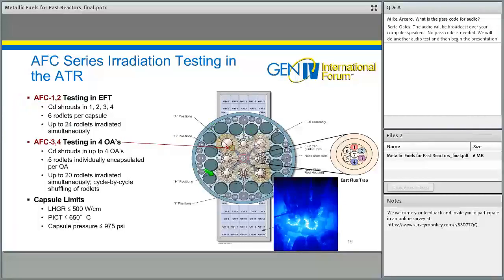So here's a cross-section of the ATR core. Initially, we were testing in the east flux trap. We've moved now to these positions called outboard A's. Here's one of the outboard A's, but there are actually 4 of them, one in each core quadrant. Within each one of these outboard A positions, we can test 5 rodlets. So rodlets are miniature rods. In the diametral dimension, they're essentially prototypic, but they're much shorter rods.